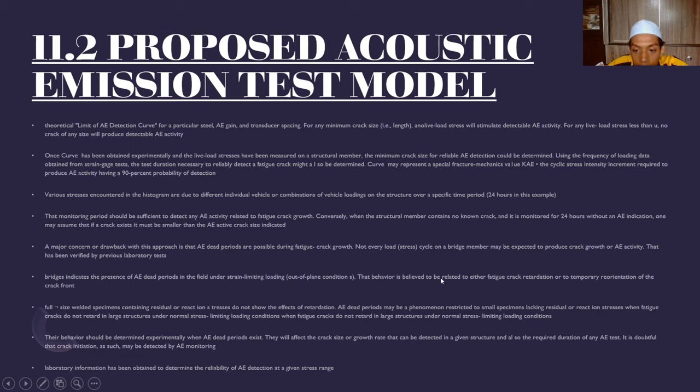That behavior is believed to be related either to fatigue crack retardation or to temporary retardation of the crack growth. Full size welded specimens containing residual or reaction stress do not show the effect of retardation. AE dead periods may be a phenomenon restricted to small specimens lacking such stress, where the fatigue crack does not retard in the large structure under normal stress.